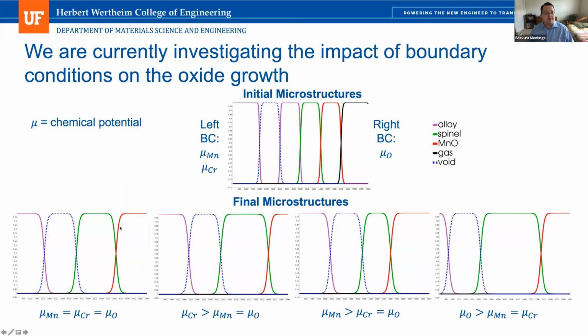And then when the chemical potentials are all equal, both the manganese oxide and the spinel phase grow at equal rates. When we have a higher chrome potential, so we have more chrome entering the system, then the spinel grows faster because there's more chrome. When we have more manganese entering the system, then the manganese oxide grows faster.